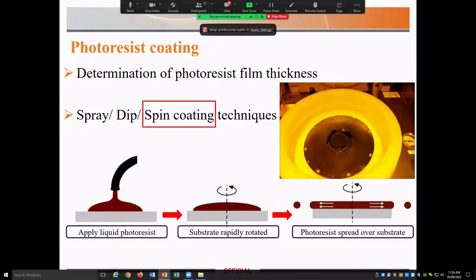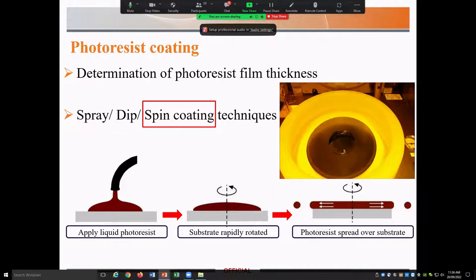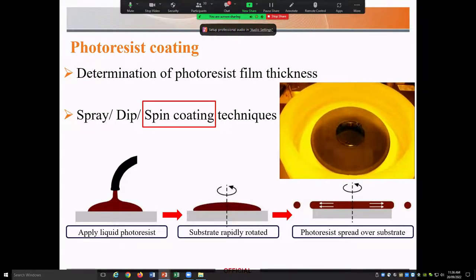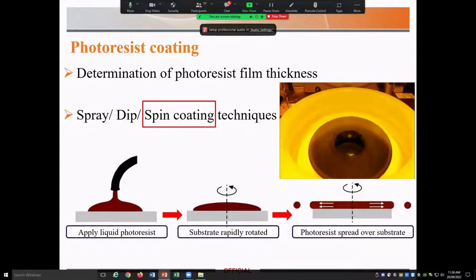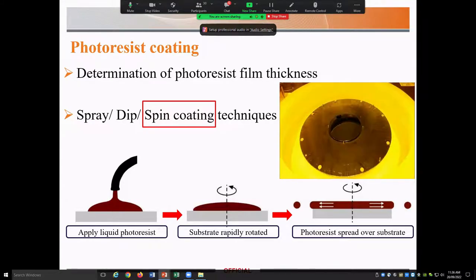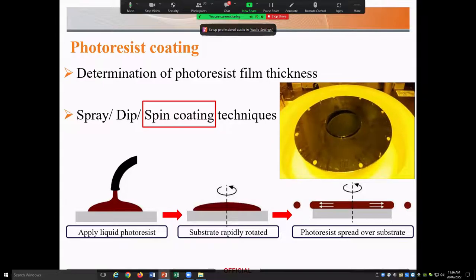So after we've got the surface ready, then it's time to coat the substrate with photoresist. There are different techniques to do that, from spray coating and dip coating, but a very common way is spin coating, where we can achieve a uniform film in a relatively short time. It is quite simple. If I play this video: the wafer is held by a chuck using vacuum. A small quantity of photoresist will be poured in the middle of the wafer and then will be spun around rapidly, and then the photoresist will be spread all across the wafer. And we will have a uniform film on the substrate.